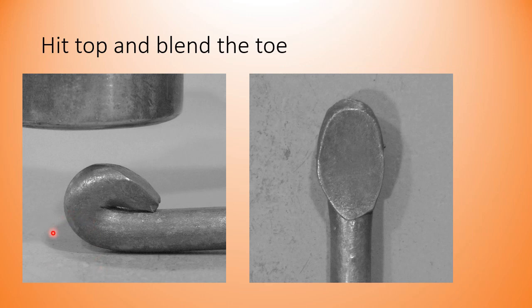You're ready to weld. You have your piece heated, fluxed, and reheated. So you're going to hit the top, and then you're going to move to the toe by angling your hammer as quickly as possible. The goal will be to blend this toe in with that first heat. Turn it over if you still have a welding temperature, or right back in the fire.